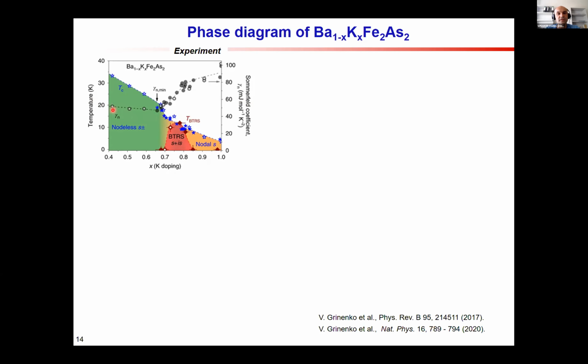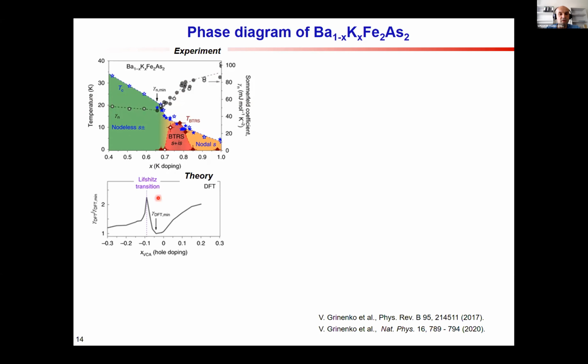At the same time, the Sommerfeld coefficient is nearly doping independent down to this 65–70%, and then sharply increases and flattens at high doping levels. This behavior of the Sommerfeld coefficient can be understood in terms of a Lifshitz transition, which appears roughly around 60% of the doping. And here are DFT calculations of the density of states. One can see that, in qualitative accord with the experimental data, the Sommerfeld coefficient is nearly doping independent at low doping levels, then has a sharp maximum, which is not observed in experiments, and then this behavior resembles the behavior of the experimental Sommerfeld coefficient.